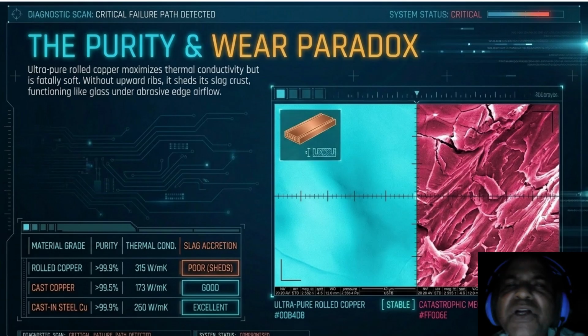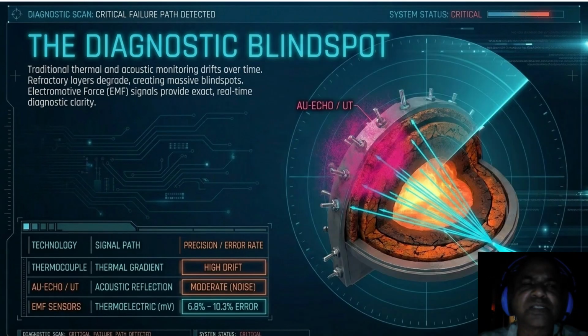So traditional monitoring is failing us because it relies on thermal and acoustic signals that drift as refractory layers degrade. On the right you see a cross section of the hearth with an EMF vector arrow cutting through a hot metal. Traditional thermocouples, as noted in the table, suffer from high drift, meaning the data you see today is not the same as the data from last year.